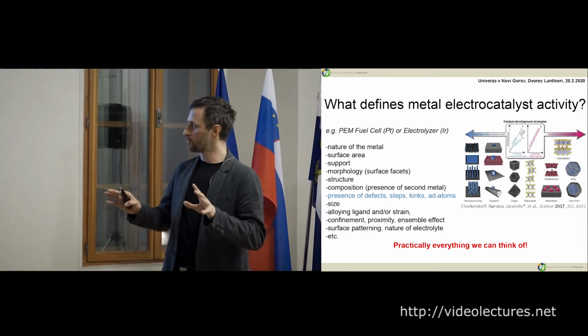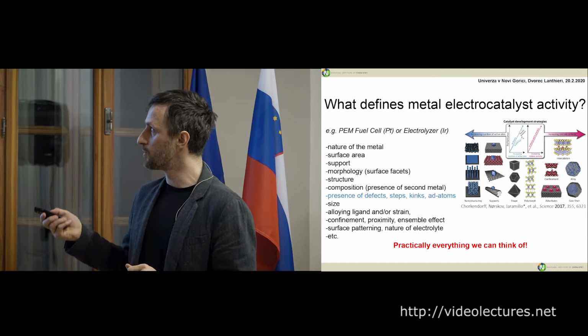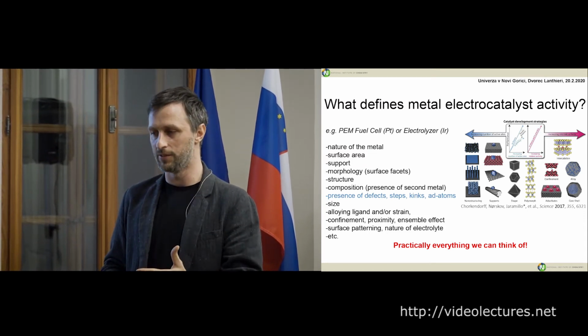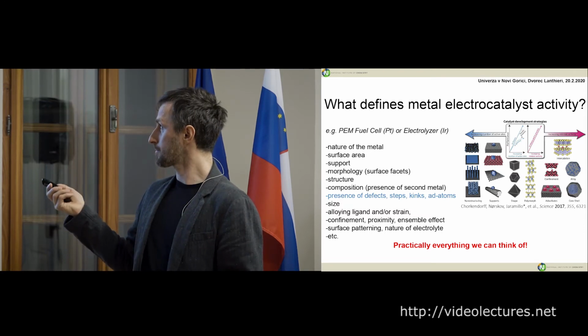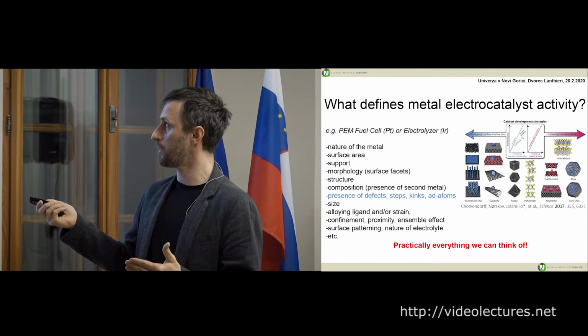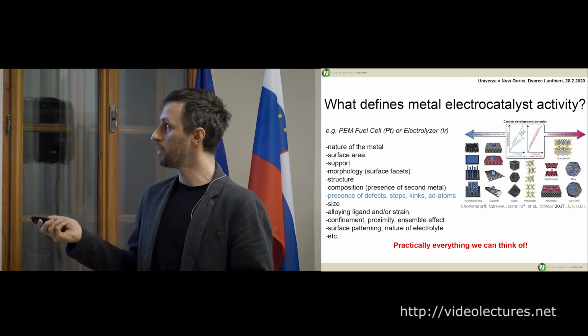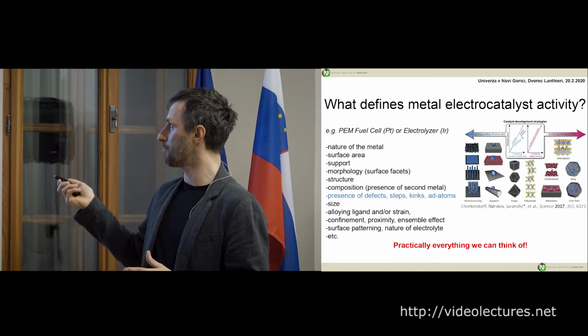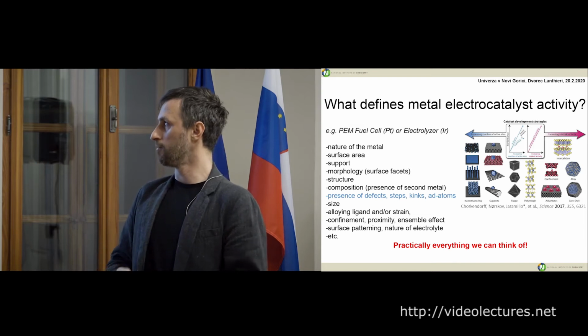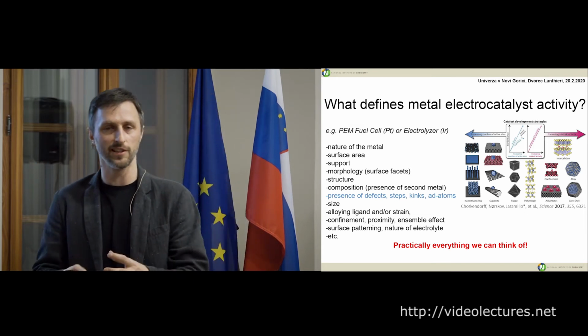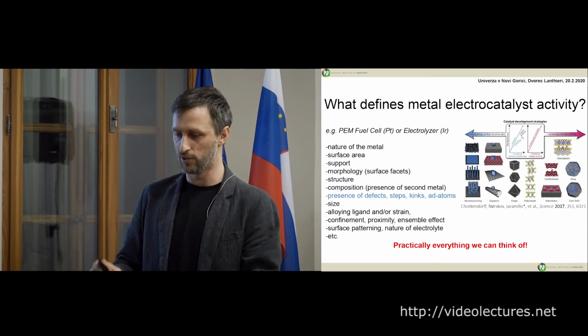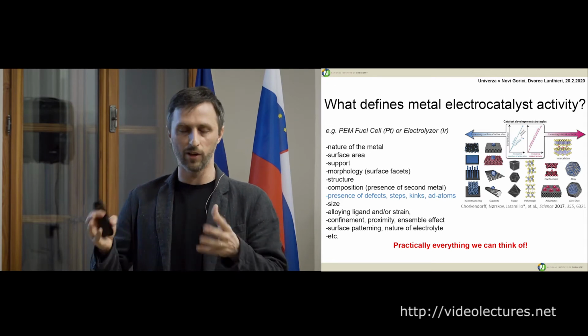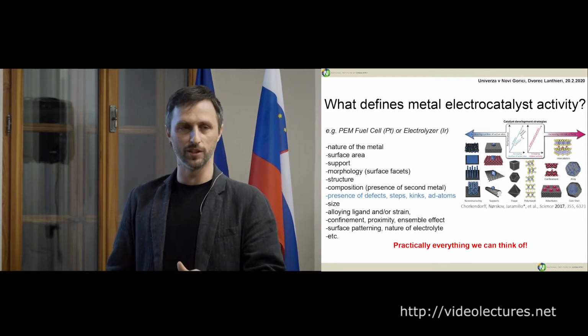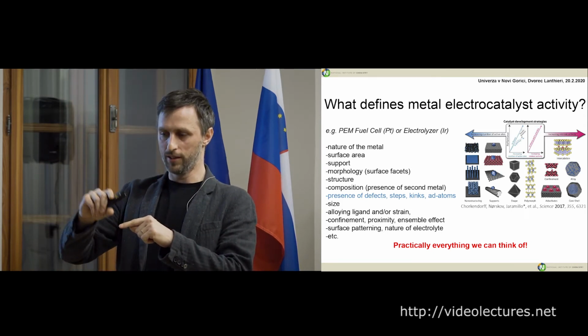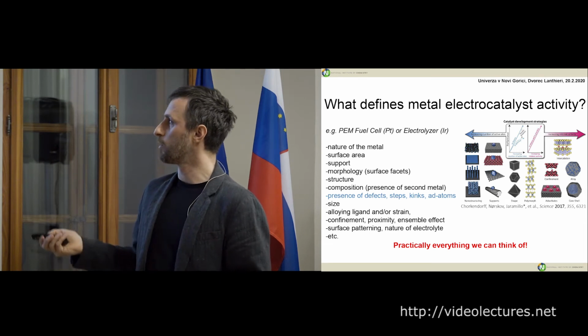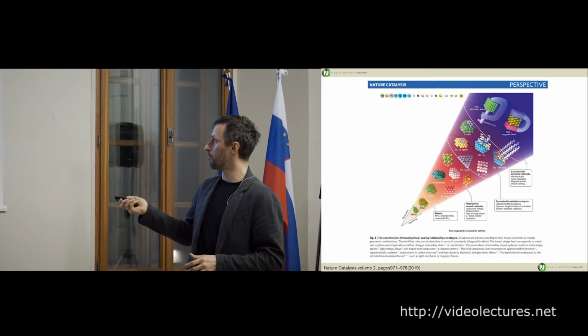Here is a slide just to confuse you, but the point is that there are many effects that influence the catalytic activity of the nanoparticles. You have the nature of the nanoparticles, support, surface area, support, morphology, structure, composition, presence of defects, kinks, adatoms, so different morphology, everything. And then you also have alloying effect, confinement effect, proximity, so practically everything. So it's very sensitive, especially in catalysis, especially electrocatalysis, to all these features. And if you're doing DFT calculations, this will change what you get out if you put in a defect or if you don't. And this is one image of how you can tune the catalyst, and the complexity just grows.